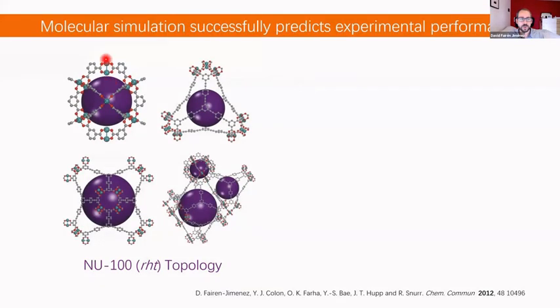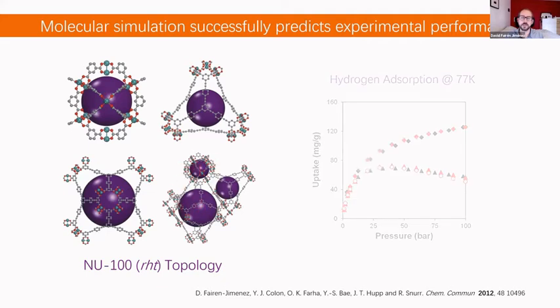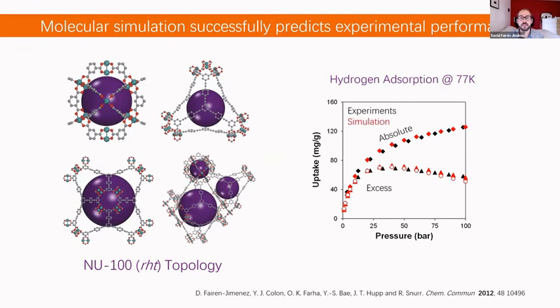Beautiful copper-copper paddle wheel clusters interconnected with this organic ligand that you can see here. And these purple spheres represent the different porosities that we can have in the material: 1, 2, 3 different pores. If we want to apply this material to hydrogen adsorption at 77 Kelvin, this is basically representing an adsorption isotherm. This is the uptake in milligrams of hydrogen per gram of material when we increase the pressure up to 100 bar. And we have the experimental data in black and the simulation in red.